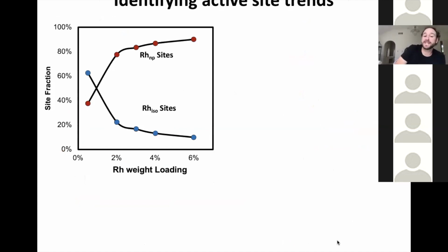We did this for that series of materials, and what you can see is that as we increased rhodium weight loadings, the fraction of rhodium exposed as single atoms dropped from something like 60%, to 20%, and down further as you got to larger and larger loadings. And conversely, the fraction of sites exposed on nanoparticle surfaces went up. This is not surprising at all. It makes sense: you're putting more metal there, so you should probably have fewer and fewer single atoms because it's harder and harder to keep them apart.